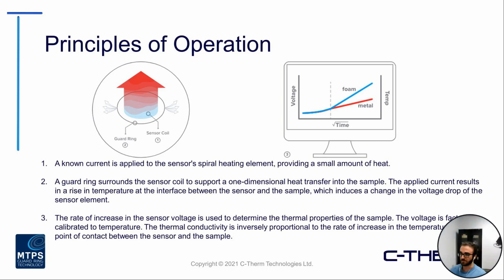So not to dive too deep into the theory today, but a high-level look at the principles of operation. The way the measurement works, first off, a known current is applied to the sensor's spiral heating element. This is on the top side of the sensor chip, and this results in a temperature rise at the sample sensor interface. You can see in the image on the right, the software is monitoring that change in temperature as a function of time, and the differences in thermal response are what's used to get at these thermal effusivity and conductivity properties.